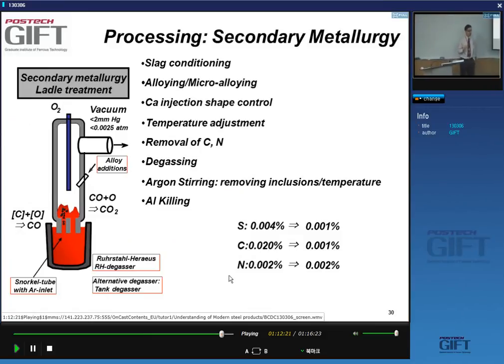There are certain situations where you want to have very, very low levels of carbon. One of the reasons may be because you want a material with extremely high formability, yes? And it turns out that in order to achieve this, you need to have very low carbon and nitrogen levels. So this is done by an addition to the ladle treatment, and it's called vacuum metallurgy.